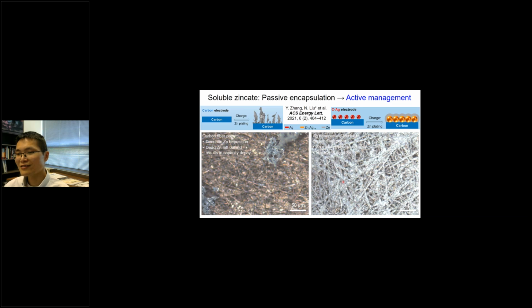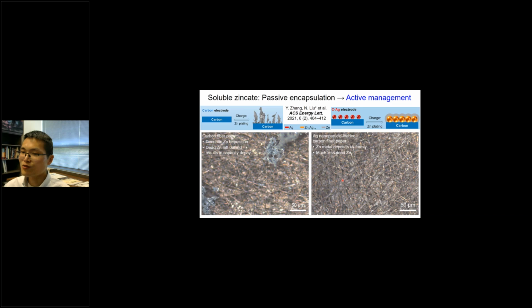Now you can see the zinc will preferentially grow where the silver is, and this makes a very uniform deposition. And there's no dead zinc formation, even in the stripping process. So this proves that you can actually actively manage where the zinc deposits by giving it some nucleation sites.